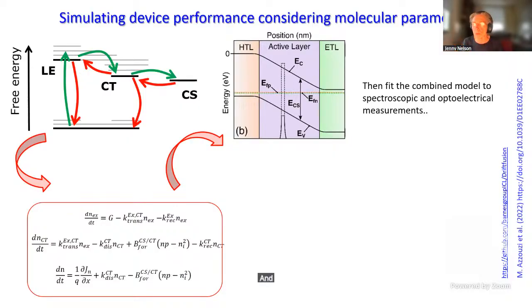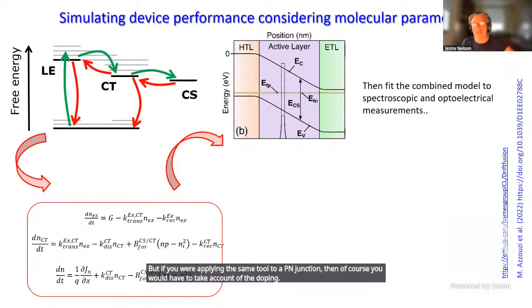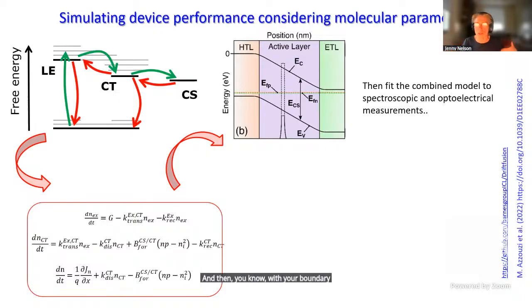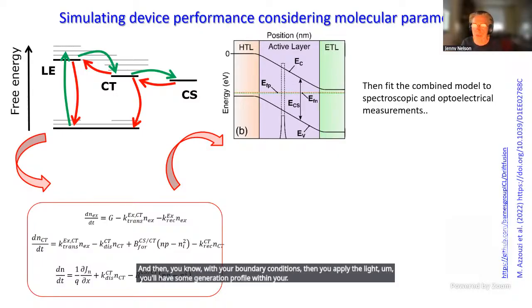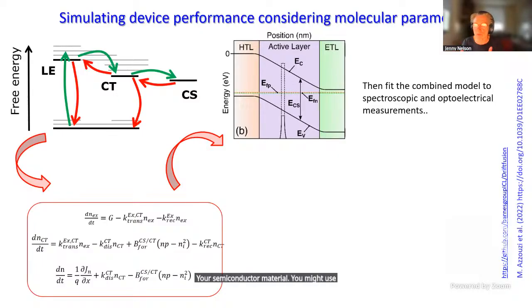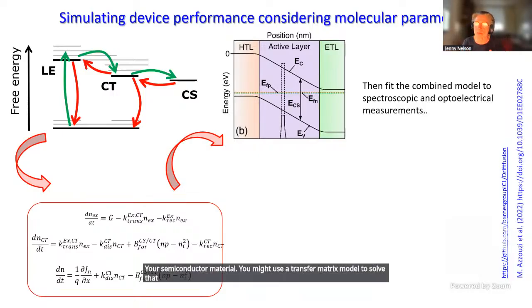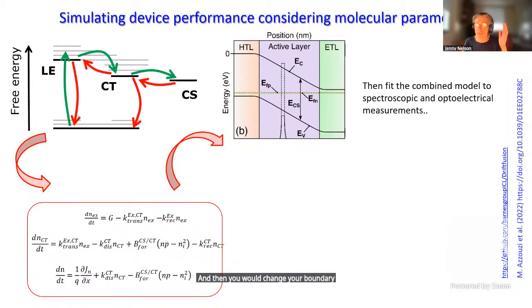You may or may not have some permanent charge present in the semiconductor material as a dopant. Normally in our materials, they're not doped, but if you were applying the same tool to a PN junction, then of course you would have to take account of the doping. Then, with your boundary conditions, you apply the light, and you'll have some generation profile within your semiconductor material. You might use a transfer matrix model to solve that if you think interference is important. And then you would change your boundary conditions. Am I in open circuit? Am I in short circuit? Am I somewhere in between?